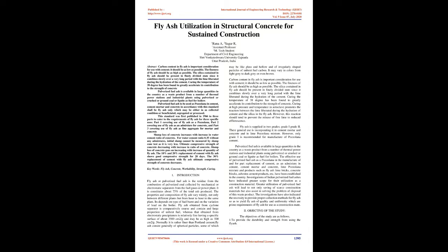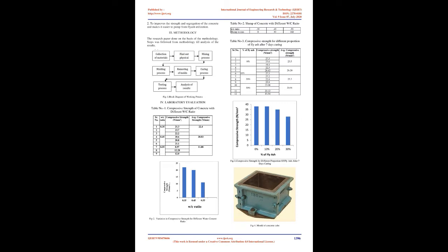Its properties depend on the type of fuel burnt and on the variation of load on the boiler. Fly ash obtained from a cyclone separator is comparatively coarse and contains a large proportion of unburnt fuel, whereas that obtained from electrostatic precipitators is relatively fine, having a specific surface of about 3,500 cm²/g and may be as high as 5,000 cm²/g. Normally it is rather finer than Portland cement. Fly ash consists generally of spherical particles, some of which may be glassy and hollow, and of irregularly shaped particles of unburnt fuel carbon. It may vary in color from light gray to dark gray or even brown.